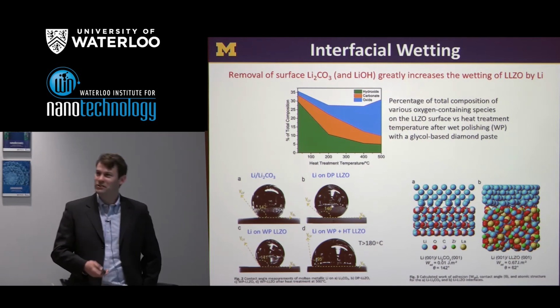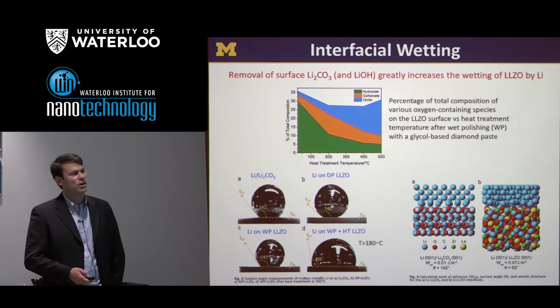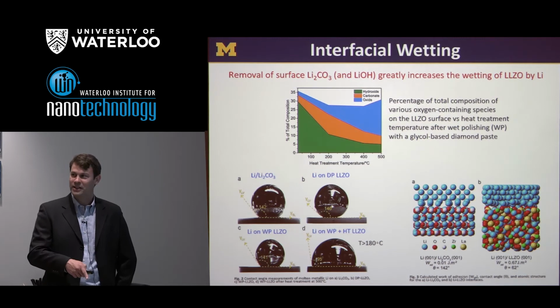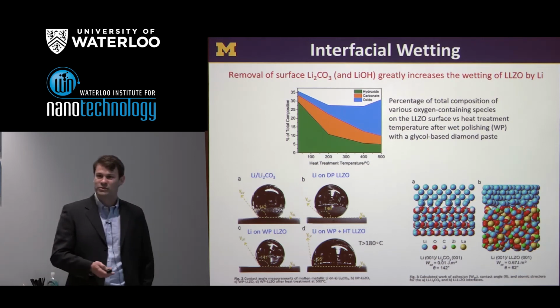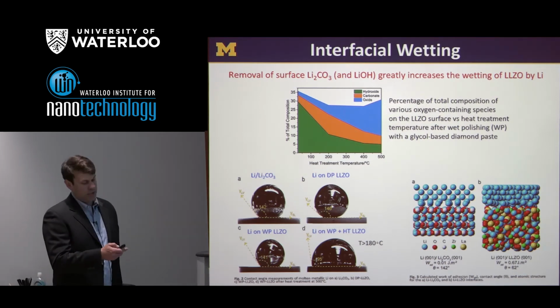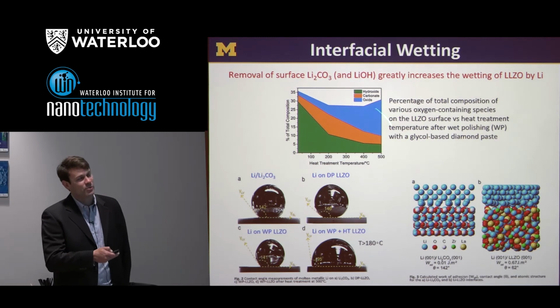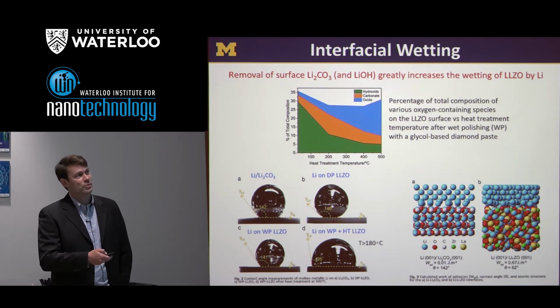One can just clean the surface of LLZO, get a much stronger interaction between the lithium and the LLZO, and basically all of the interfacial resistance goes away. So this is some work done also in collaboration with Neil Dasgupta and Jeff Sakamoto.